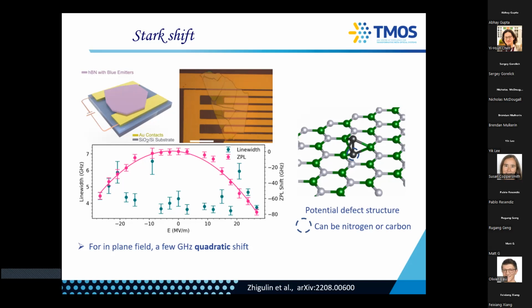And these atoms can be carbon, okay, can be nitrogen. The DFT calculation suggests that both configurations are stable. Because we only work with multi-layers, there's no problem with stability there as well. And for full disclosure, we have never seen anything in a true monolayer of hBN. Okay, so that's a big challenge we can discuss a bit at the end.